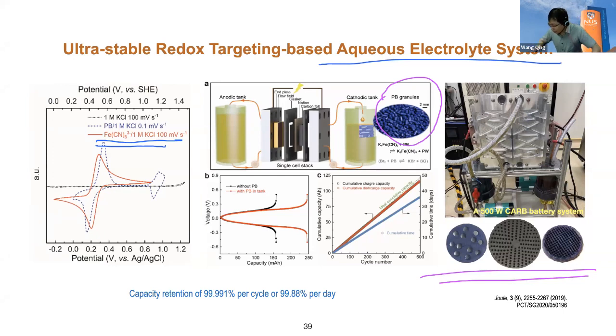And in the photo shown here, there's a 500 watt system, and on one side we have this Prussian blue honeycomb solid, just put in a tank, and the ferricyanide electrolyte flows through the material, so it enhances the capacity. Okay, and this system is extremely stable. There's no capacity drop in a few hundred cycles.